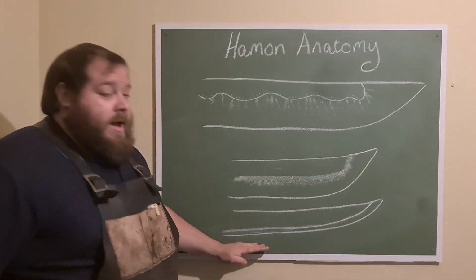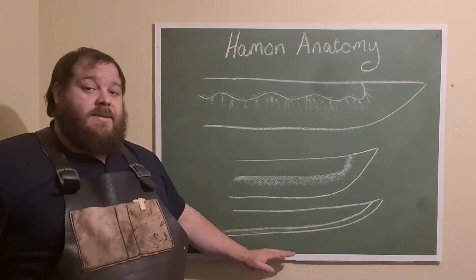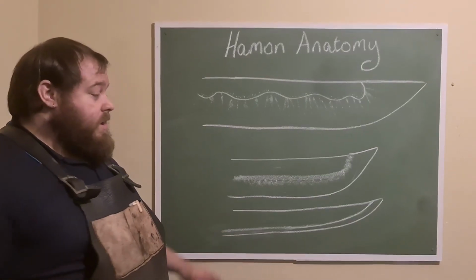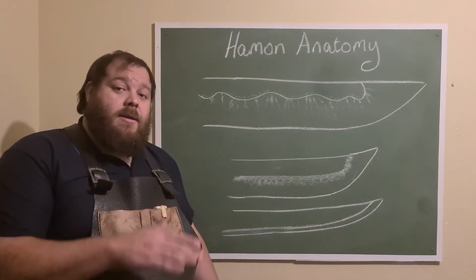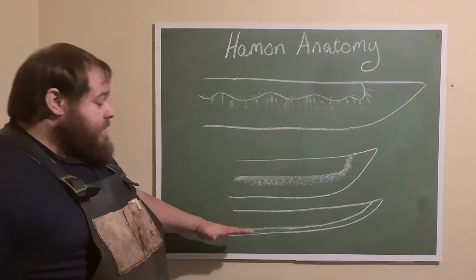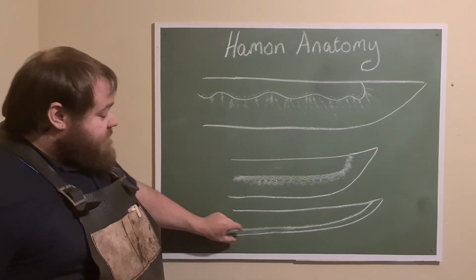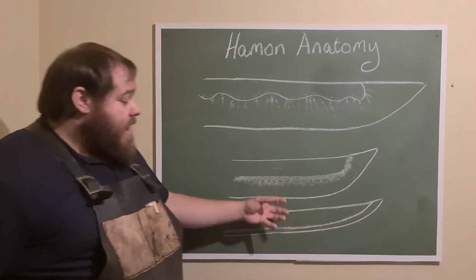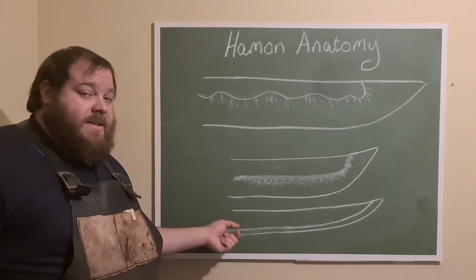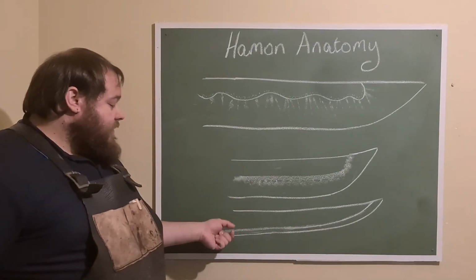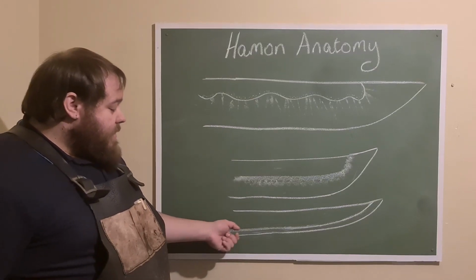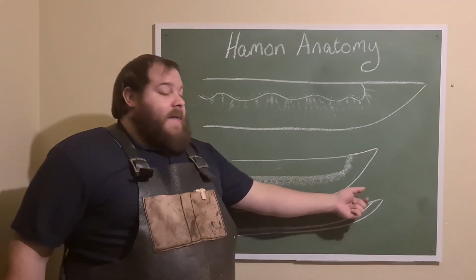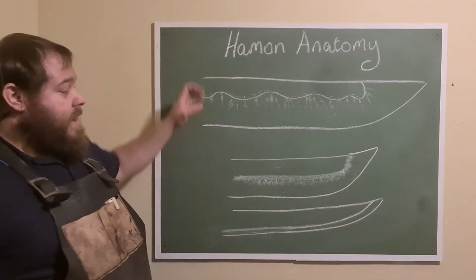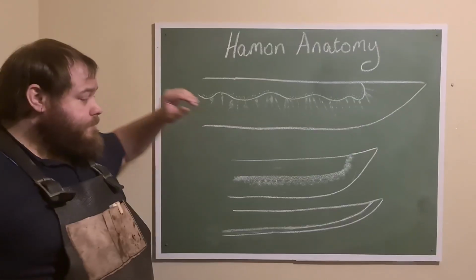Then you've got the really hard line, and this is normally done by differential hardening, by quenching in a thin pan or something very shallow and only dipping the edge. And that's why you get that very hard transition line. That hard transition line, again, is still going to have that softness to it. It is still going to have some of that carbide coming out in that line, but that is going to be your hardest transition compared to any other form of Hamon.